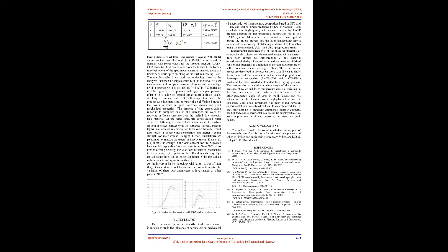According to Table 6, the minimal calculated value of the final coefficients for Latp-UD2 is 49.20. So, the response function with 5% error is represented by equation 5. By analyzing the regression equation, it should be noted that also in the case of samples Latp-UD2 the main positive contribution to y is given by the laser temperature and the compact pressure of the roller. The influence of the laser angle and the interaction of the 2 and 3 factors affect the flexural strength insignificantly, and these factors, x1, x1x3, x2x3 and x1x2x3, can be omitted in the regression equation.